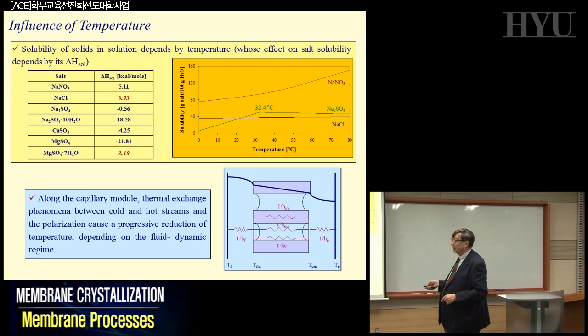Remember we talked about the problem of temperature polarization in membrane distillation, very present here and more. One of your PhD students today in ITM is working only on temperature polarization profile in membrane crystallizers, because you have a lot of these temperature polarization profiles that you are forming, related to the thermal properties of the material, that means your polymer, and to the heat transfer across the pores of your membranes, depending on how big they are, etc. You can have a different form of temperature profile, which can affect not only the efficiency, but also the final performance of the system.